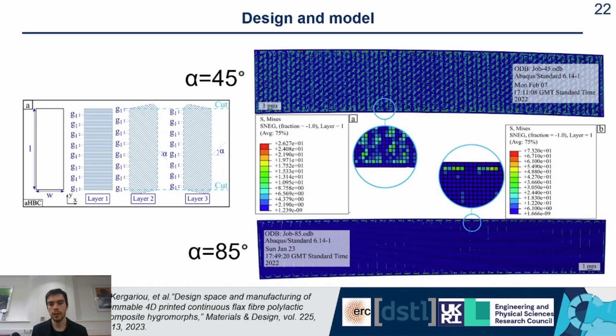The other benefit is that it enables you to understand the local actuation of your material. So this is a specimen that I've already talked about in the past. One with 45 degrees on the top and 85 degrees at the bottom. And this is the model that we've created applied to this type of actuator. So this is an FEA model, so the yellowish, reddish colors represent high stresses, while the blue represent low stresses. And with this model, you are able to understand exactly the spot where your actuation comes from.